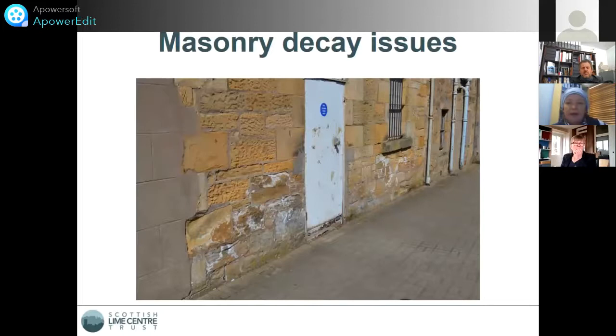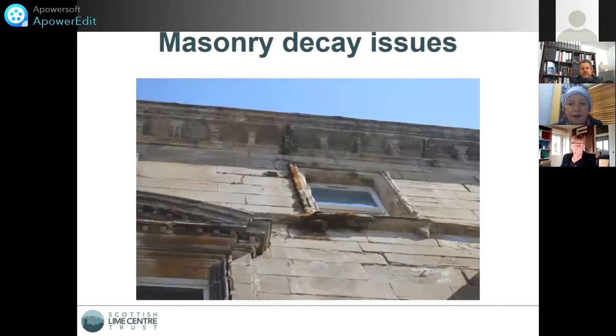Back again to masonry decay issues, and you can see here the effects of de-icing salts on this sandstone wall at the base of the walls, not helped by the judicious amount of cement pointing. And usually salts that crystallize on the surface of stone are fairly harmless. They just get washed off or brushed off with rain. But over time they can cause serious problems of masonry decay. And we've just got a few other shots here.